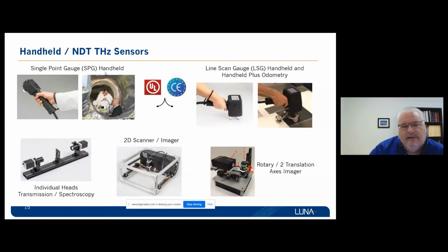This is just showing, again, some more of the applications. The upper left-hand corner, thickness measurement being used to measure specialty coatings inside an inlet duct, transmission spectroscopy in the lower left, 2D scanner for C-scan image in the middle bottom. We have done measurement of bottle wall thickness, which is not necessarily an aerospace application, but examination. And then what we would call the line scan gauge, which can either make cross-sectional B-scan images or 2D images.